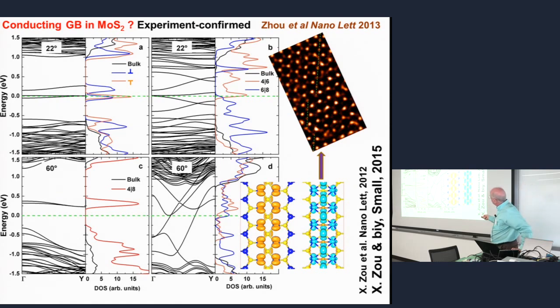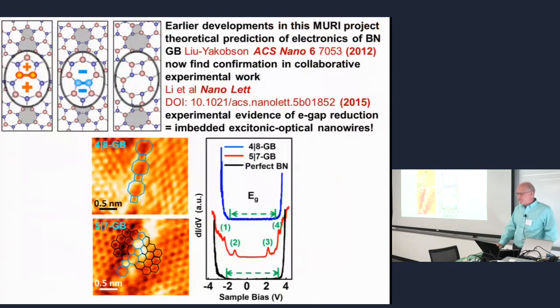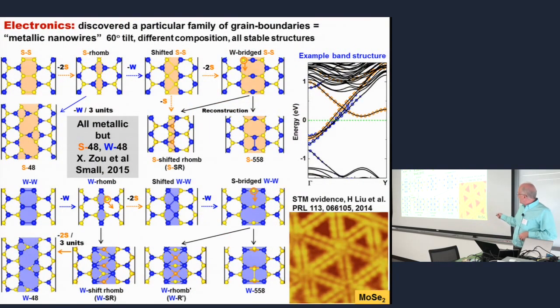So first we bumped into this in this work. We found just one, and we thought, oh, this is interesting. Then we did full classification. So actually, most of inversion grain boundaries are like this, when it's 180 degrees misoriented. If you take moly disulfide or any of them, 180 degrees misorient, this will be a grain boundary right here. For graphene, it's pure, no grain boundary, because graphene is inversion symmetric. But these guys have no inversion symmetry, so you have grain boundary. And most of them are metallic. So these structures are now observed in experiments, so it's quite interesting, this patterning.